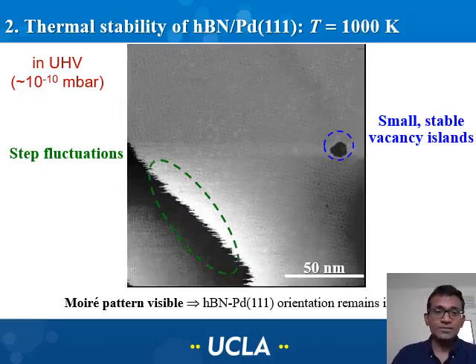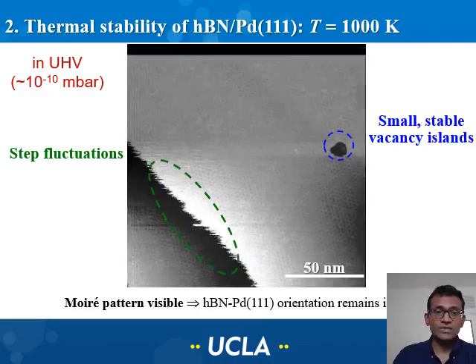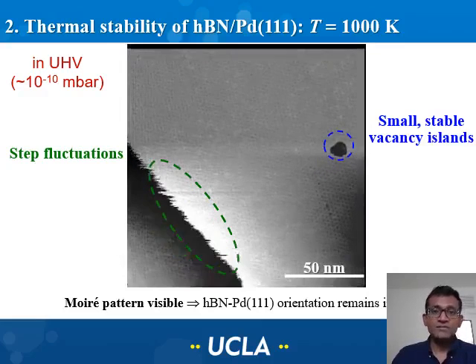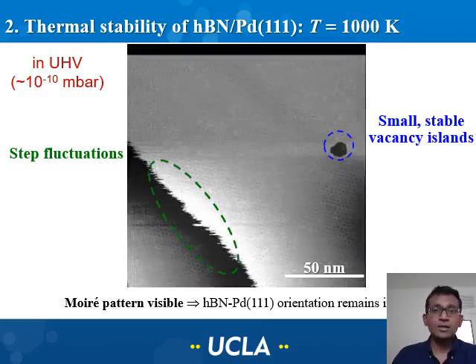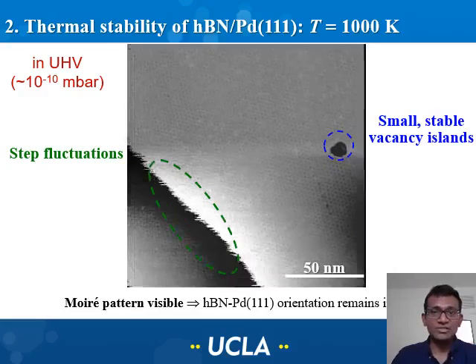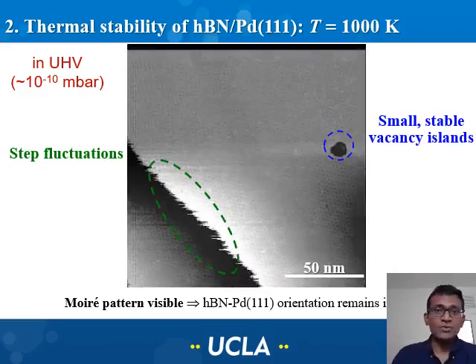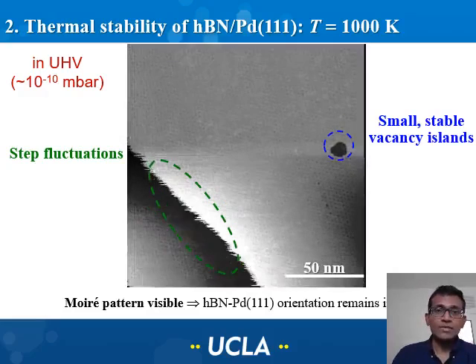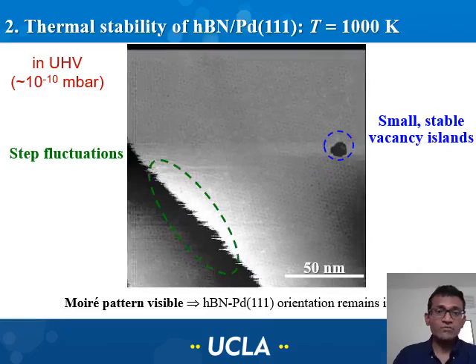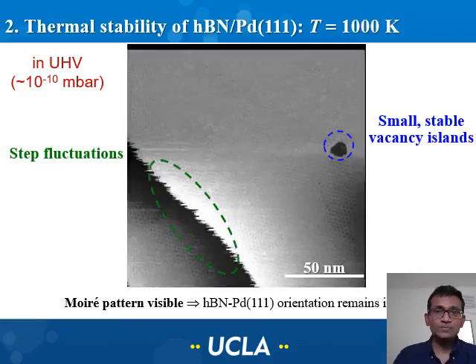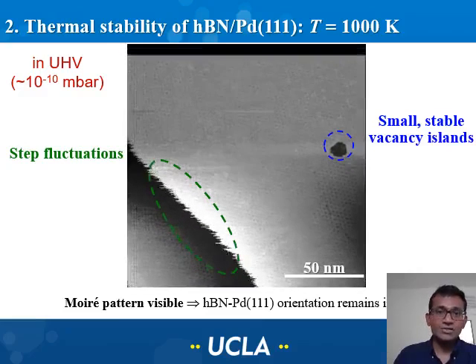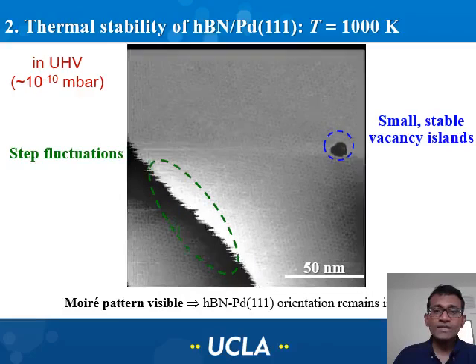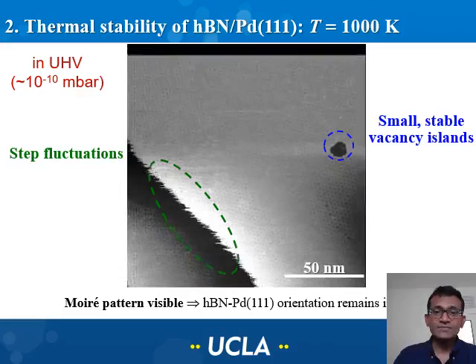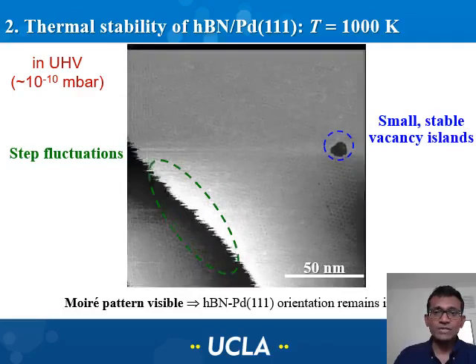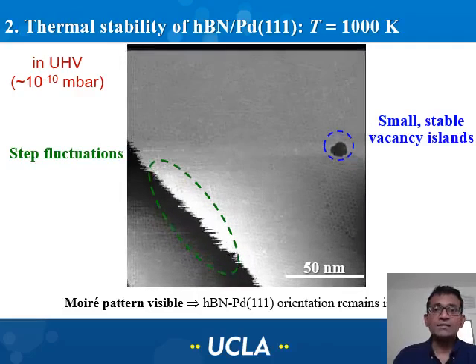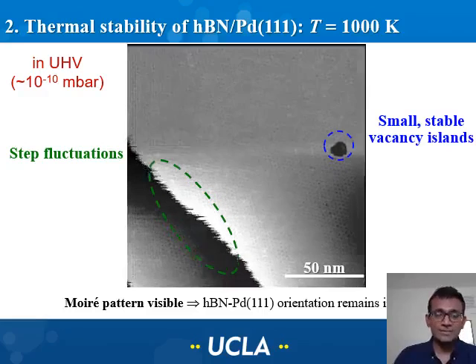And the other aspect is these fluctuations that you see along the step edges, which is indicative of atom motion along or across the step edges that give rise to these thermal fluctuations. So even though there is a boron nitride layer covering the surface, we do see fluctuations, meaning there is atom motion on the steps under the hexagonal boron nitride. And interestingly, this vacancy island, which is very small, about 10 to 20 nanometers in size, changes little at this high temperature.